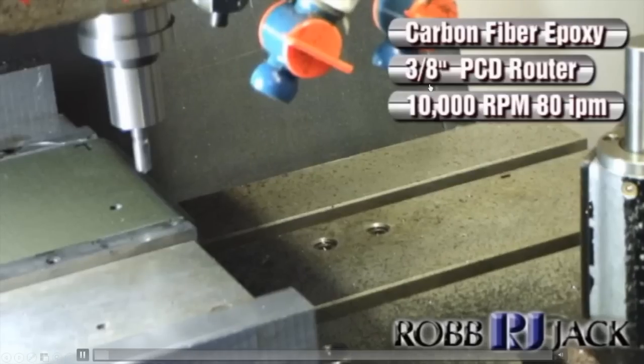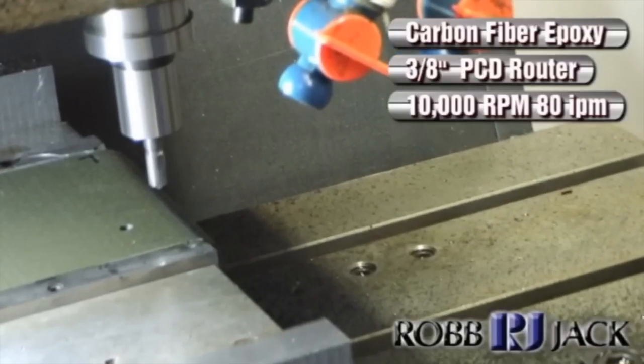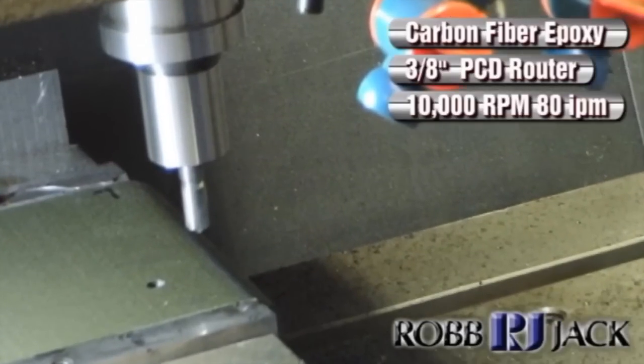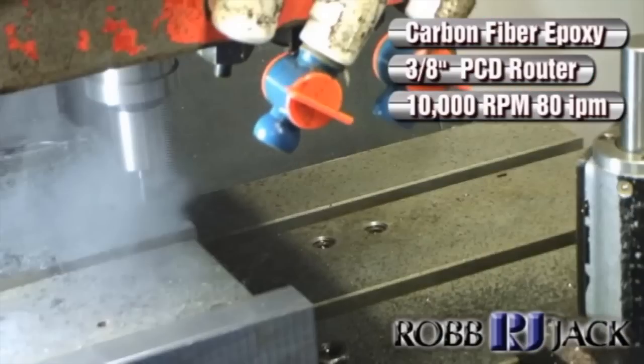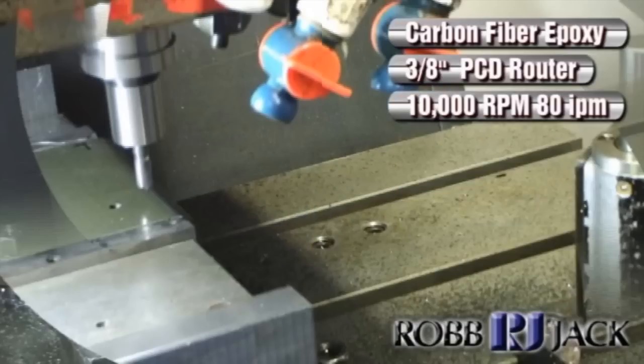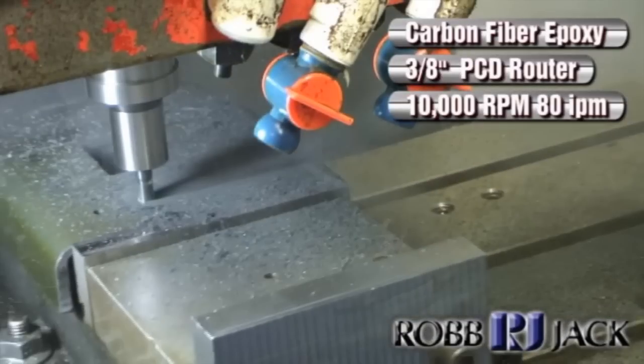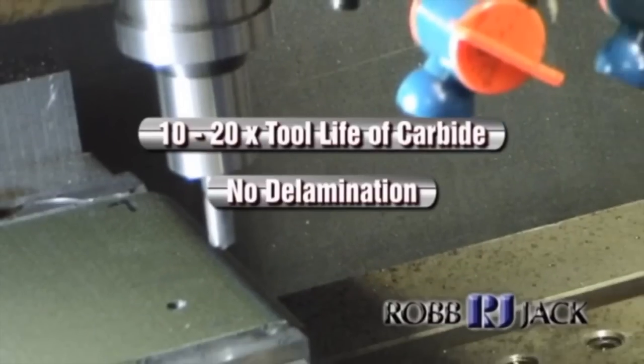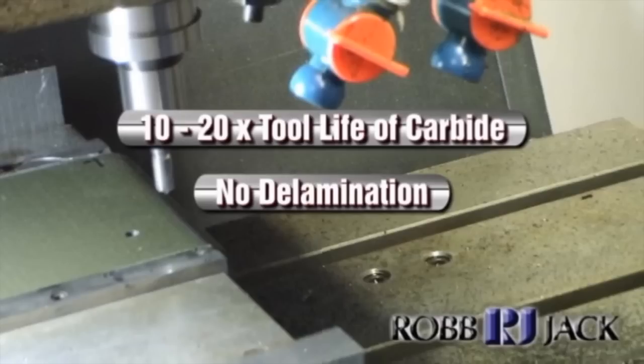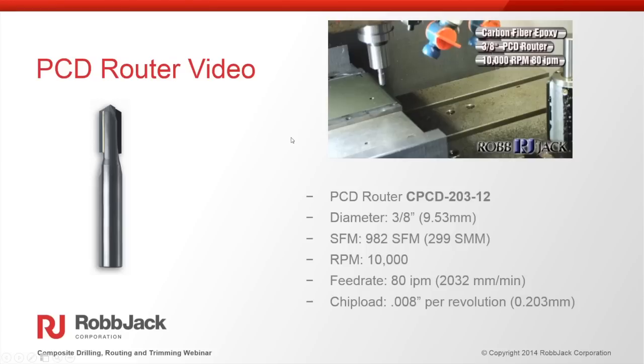I'll go ahead and play this video one more time so you can see it. The tool goes down one shot, cuts it to shape in one pass, and when you look at this part, these edges are extremely clean, sharp. There's no uncut fibers, no delamination, and we can hold very tight tolerances. In some of the talks that I've done, people are a little bit reluctant on going to one pass right to size. And in most aircraft applications, that's what I find: once you get a good tool and a good operation, you can do it. You typically do not have to do any finishing operations. We can hold most tolerances a lot tighter than what is required doing it in that one pass.